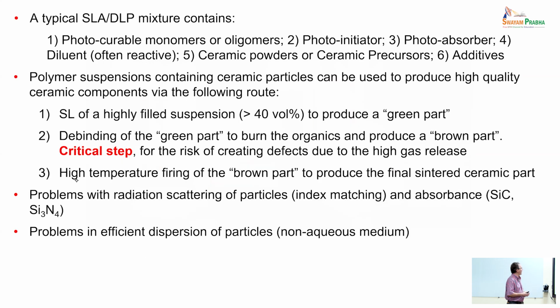The issues that you have, and first, let me mention that in order to use these technologies for ceramics, and I'm talking about conventional ceramics, not precursor-based ceramics, you need to have photocurable monomers or oligomers inside your feedstock. You need to have a photoinitiator. You need to have a photoabsorber that allows you to control the penetration depth of the light, and therefore the quality of the part, or certain features inside the part. You might add a diluent if you need, or other additives, but you certainly need to have ceramic powders. And if you have ceramic powders, what happens is that you increase dramatically the viscosity of the slurry.